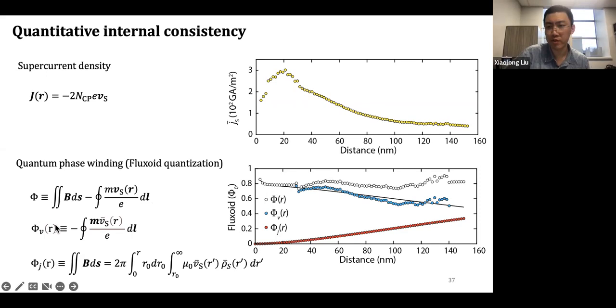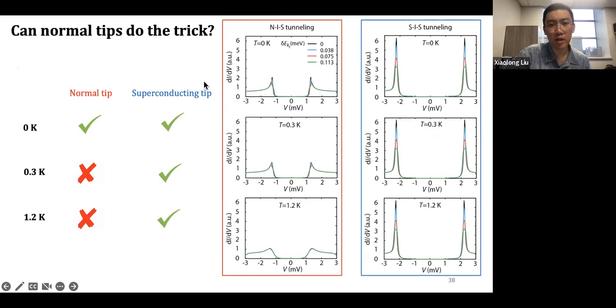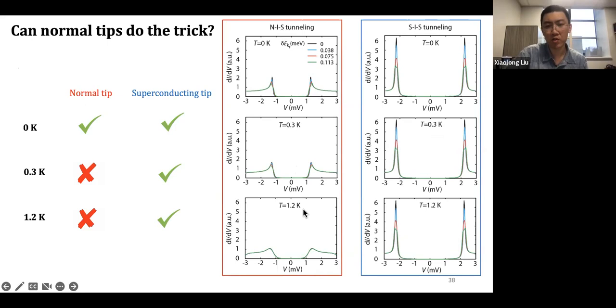You may wonder why we use a superconducting tip for the Doppler effect measurement. The reason is simulated: in normal or superconducting tip tunneling with a superconducting sample, at non-zero temperature, smearing due to the Fermi-Dirac distribution at zero energy makes normal-tip spectra overlap and become very similar even if the Galilean energy boost is different. You can't tell the differences at 0.3 K. But in the S-S tunneling regime, because you avoid the Fermi-Dirac smear at zero energy, you can have very sharp peaks up to 1 K. That's why we choose to use a superconducting tip.